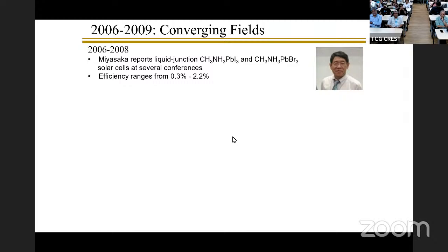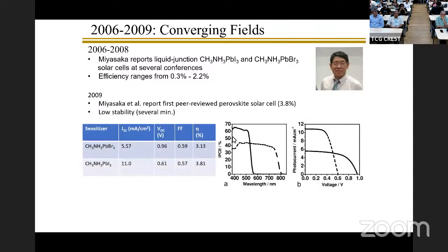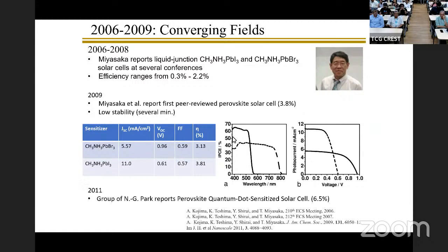Unfortunately, all his attempts ended with a very small percentage of efficiency, and nobody was looking at these papers. These papers couldn't get published. They were only being published in conference proceedings. Not only was the efficiency very small, but it was also very unstable. I'll talk about that in a moment. Then with some effort, he pushed it up in 2009 to get it slightly higher, about 3-4%, which got published. And then in collaboration with Nam-Gyu Park, they published in 2011, where he could push it up to 6.5%.